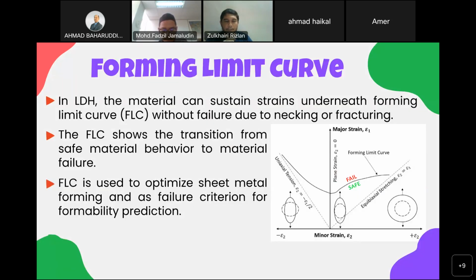So from the limit dome height test, forming limit curve can be plotted by using the strains. In limit dome height, the material can sustain strains underneath forming limit curve without failure due to necking or fracturing. Forming limit curve shows the transition from safe material behavior to material failure, and it is used to optimize sheet metal forming and also as a failure criterion for formability prediction.